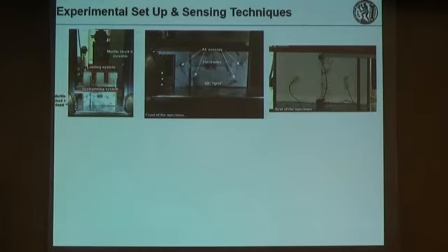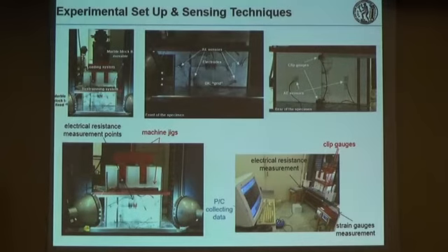We also used the acoustic emission technique. 8 different acoustic emission sensors were placed at strategic locations around the specimens. And we also performed digital image correlation in order to capture the displacement field at the front of the specimen using 2 different cameras. And at the rear of the specimen, 2 clip gauges were placed to monitor the relative displacement of the 2 marble blocks, and here you can also see 2 more acoustic emission sensors. And I would like to show you some pictures of the experimental setup.